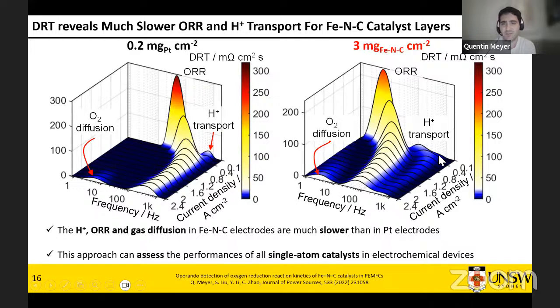Here it's two peaks. This peak is proton transport in the membrane. This peak is proton transport in the catalyst layer. That indicates that it's a much, much slower mechanism. Now, when we look at the reaction, we went from a peak of about 50 Hertz to somewhere around 5 Hertz, which shows we have a much slower process. And again, gas diffusion, although it's not as impacted, seems to be going at a slower rate.